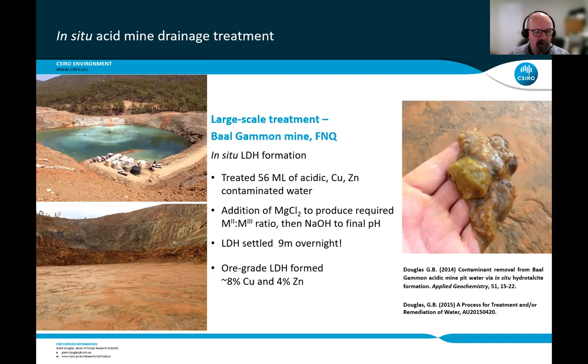So we were then able to treat that water with reverse osmosis and discharge that water over the side of the pit. One of the other important things was that the initial concentrations of copper and zinc were 40 and 20 milligrams per litre respectively, but with those high concentration factors that I talked about, we're able to form an ore grade layered double hydroxide. There's in fact about twice the ore grade of the pit that they were mining. So we had about 8% copper and about 4% zinc. And so that opens up the possibility of being able to reprocess that layered double hydroxide and get metal values out of it to offset some of those treatment costs.